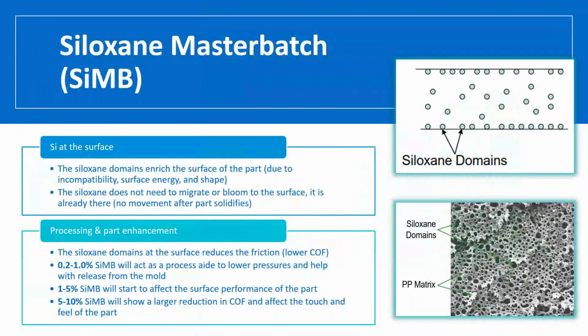Okay, and then kind of how it works, as I mentioned, it ends up on the surface. And so it's already there, it doesn't have to migrate there, it ends up on the surface. So when it freezes off, cools off, is done being processed, it's at the surface to do its job. And that's what gives you your low COF because it's already there doing its job. The other thing to note here is using it at different percentages will result in different functions.